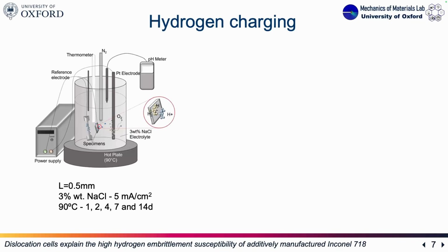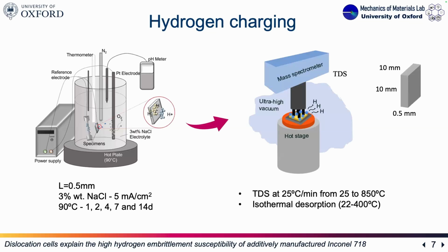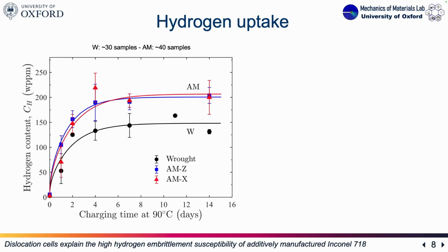So what we have done is hydrogen charging, an electrochemical technique, because at that time we didn't have the gaseous charging setup established in our lab. So we tried to introduce as much hydrogen as we could, trying to saturate the samples. That's why we chose small thicknesses. And then we performed TDS to do the trapping analysis and determine the hydrogen diffusivity of both alloys.